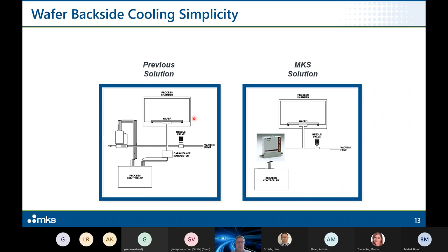Here's an example for upstream pressure control. It's called wafer backside cooling. You see here our wafer in the process chamber, and the wafer is held on the chuck with electrostatic forces, and on the backside there is a helium atmosphere applied. The helium atoms, because they are very light and very fast, give us a very good heat transfer from the wafer to the walls, so we can remove heat which is introduced by the process very fast from the wafer.